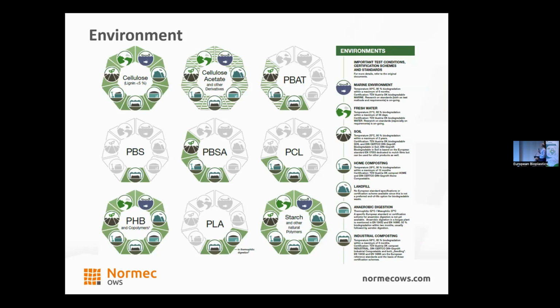We will also update it. It shows in which environment each material will degrade. So cellulose is a natural material and can degrade in any environment. This is the same for PHB, already discussed from the project before. For PLA, it's interesting, only two environments are considered here. This is industrial composting and thermophilic anaerobic digestion. Why? PLA needs this thermal trigger to start the degradation, to start the hydrolysis, and to be completely biodegradable. PBS also not that much, and PCL, you see mainly in soil and industrial composting, but depending on the application, on the type, it can also be in water conditions.